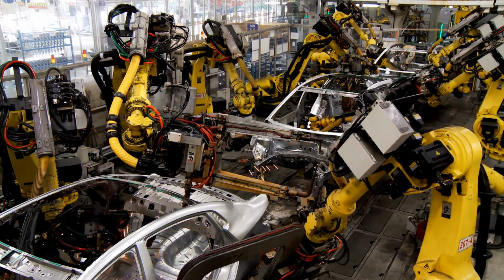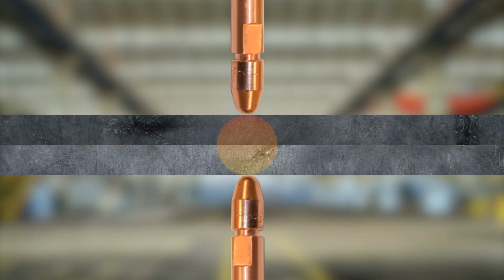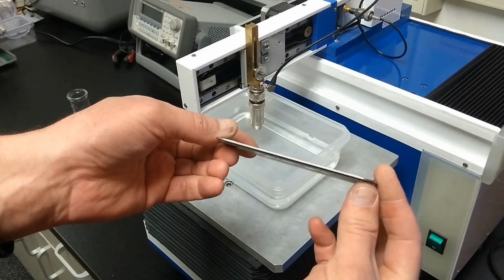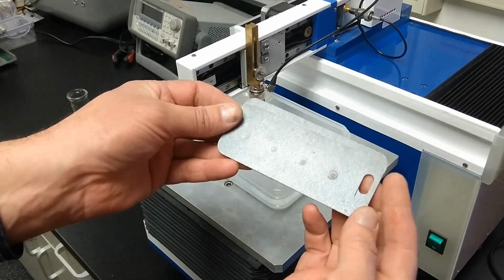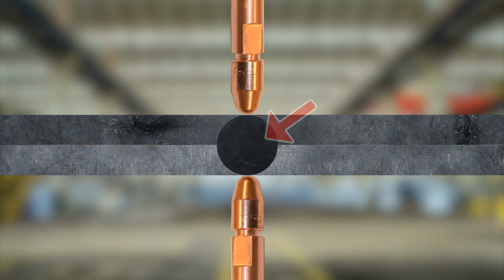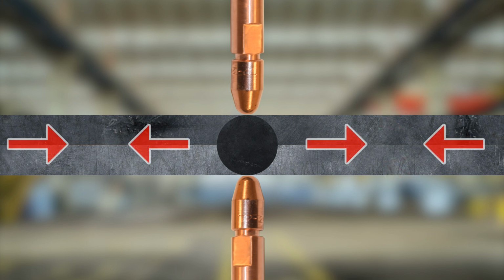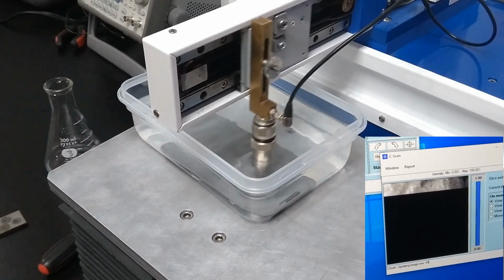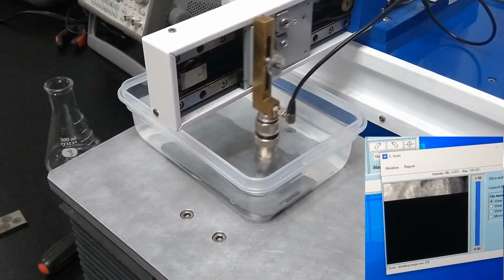In the spot welding process, the metal from the two plates is melted together in order to form a fused area of metal. This is known as the weld nugget. Because this sample has areas of continuous metal, the spot weld nugget, as well as two plates separated by a gap, the unwelded area, the signal from the transducer will respond differently based on these two areas.